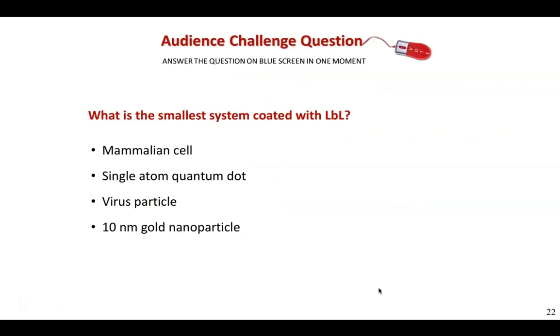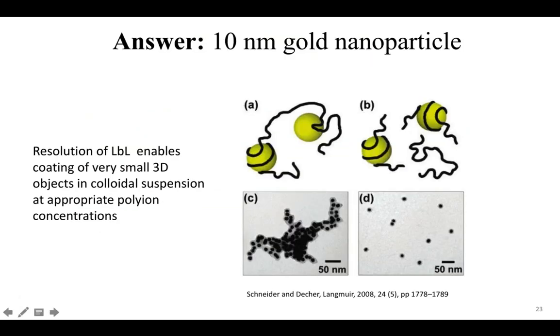Excellent. It turns out that the smallest system that's been coated so far that's been reported is a gold nanoparticle. And some of the smallest have been between 5 and 10 nanometers. This is actually rather fascinating because these polyelectrolytes can wrap around extremely small nanoscale material systems.